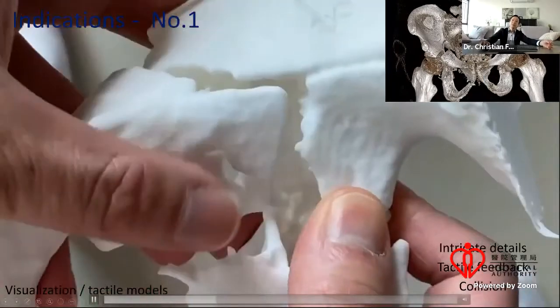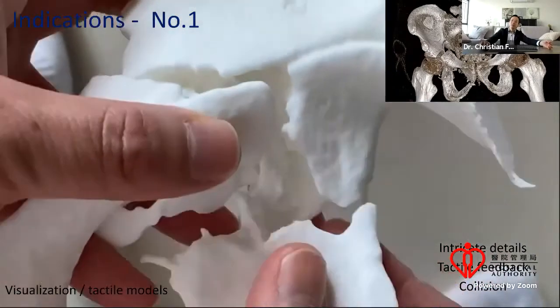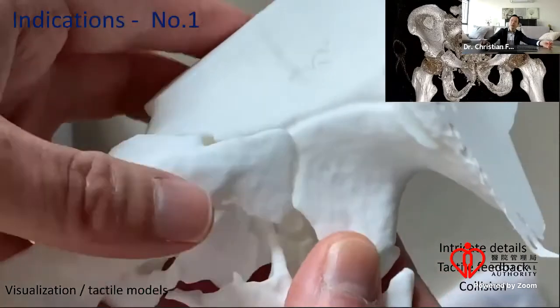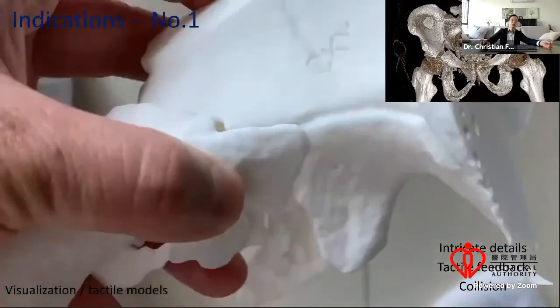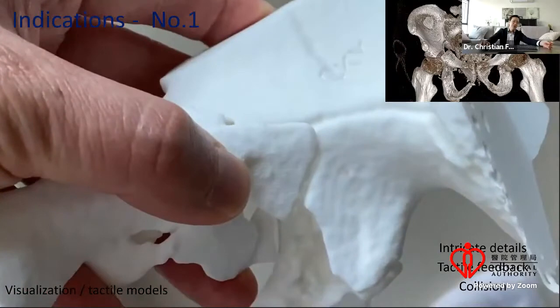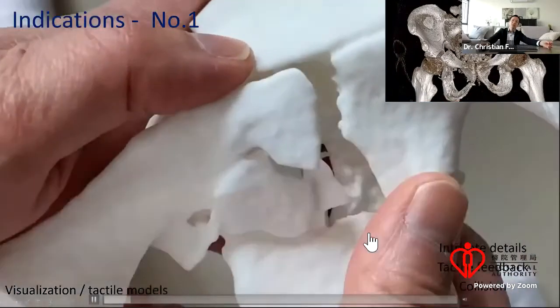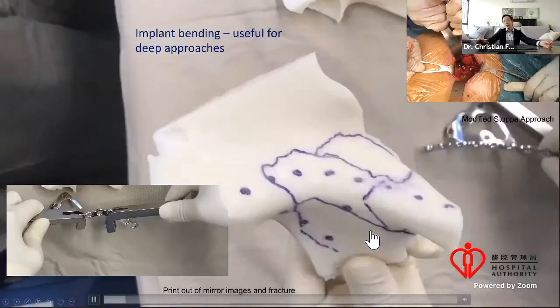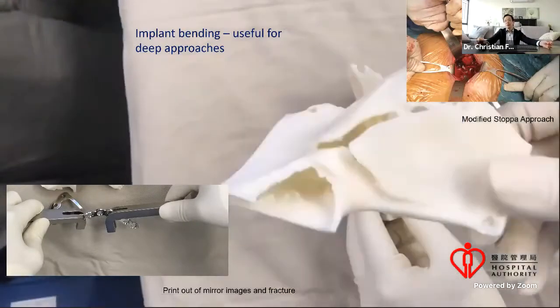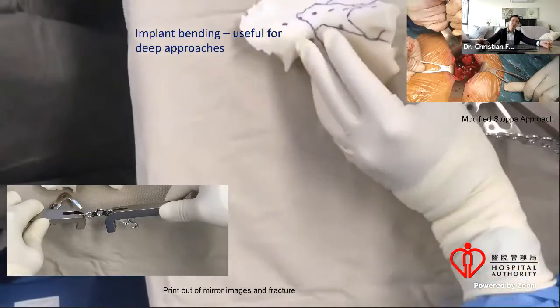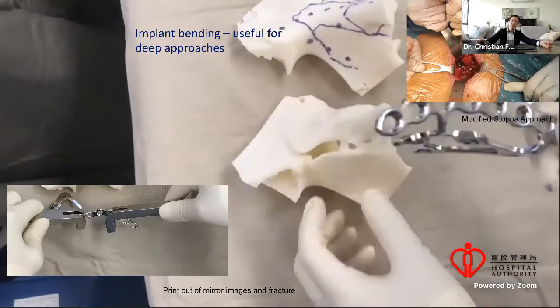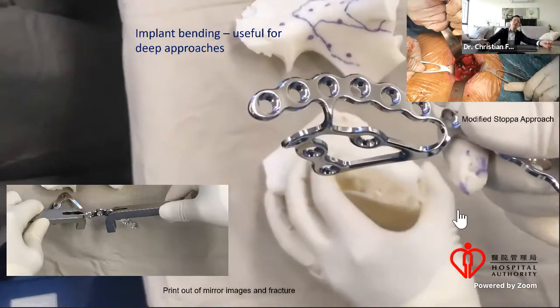You can see these details, very intricate details. It gives you tactile feedback, collision control, so I can know how I can treat this complex acetabulum fracture well during surgery. And also, moreover, these are high temperature sterilizable. So 132 degrees steam autoclave, no problem. The previous FDM products, you cannot do steam autoclave.